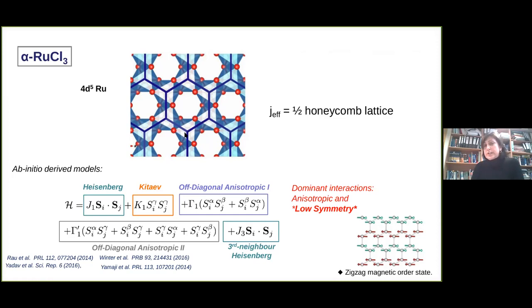So for instance, if you consider yourself in this bond with an SZ-SZ Kitaev interaction, the gamma contribution would be, for these two nearest neighbors, SX SY plus SY SX. There is also a small gamma prime term, which would be for the same bond terms like SZ SY and SZ SX. Moreover, we have a small contribution of Heisenberg terms, nearest neighbor and third nearest neighbors. And when you consider all this set of interactions, one can describe the properties of the system. For instance, the fact that at low temperatures, the system is not a spin liquid, but it orders, it has long-range magnetic order in a zigzag way.